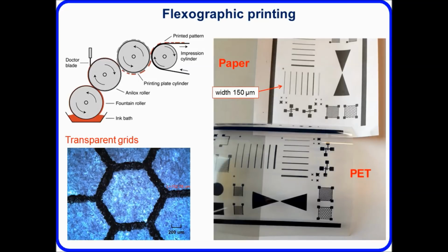We can also print some kind of transparent grids. So although the inks are quite thick and they appear black, we can actually print mesh structures, which might be useful as electrodes in organic photovoltaics. And again, with this technique line widths can be printed down to around 80 microns. So the resolution is slightly better than with screen printing, but typically the printing thickness is around 1 micron compared to around 2 to 3 microns with screen printing. So we're printing slightly thinner layers.